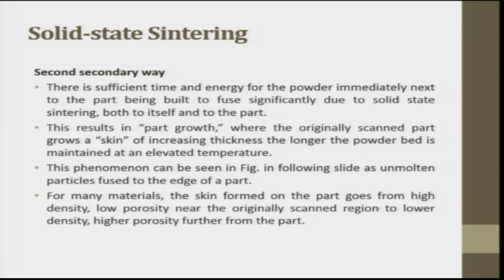There is sufficient time and energy for the powder immediately next to the part being built to fuse significantly due to solid state sintering, both to itself and to the part. So next to the part there will be sintering happening. This results in part growth, where the original scanned part grows a skin of increasing thickness the longer the powder bed is maintained at an elevated temperature. This is what they call a skin, which is getting stuck to the surface. This phenomenon can also be seen in the next figure, as an unmolten particle fused to the edge of the part.